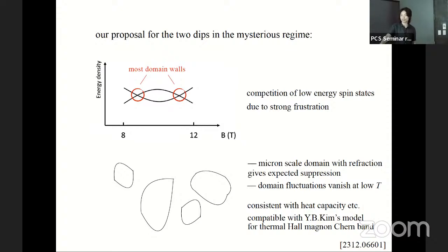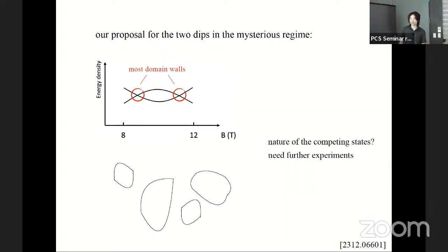And moreover, this is compatible with Y.B. Kim's model for thermal Hall magnon Chern band, because in that model they needed the frustration, and then it will have a lot of competing low energy states. Maybe not exactly their competing low energy states, but at least it's compatible with theirs. So it's also compatible with the thermal Hall theory. So we find this is the simplest, really very simple explanation, but we excluded a lot of other possibilities and found this is the simplest possible explanation.